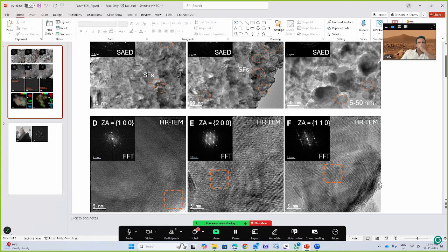Okay, my feeling is we can dig very deep and all this stuff, but we need to finish it. Is the mobility intrinsically low or not is the key question. Thermal conductivity is still pretty low, 0.6 is pretty good. So if we can get to a regular semiconductor level, and this is clearly a semiconductor, 0.4 eV band gap, we need to think about what we need to do to increase it. So if Mahesh's point is true, maybe we might be okay with annealing, compressing under slightly higher temperature. Higher temperatures are okay, with a small amount of impurity phase.